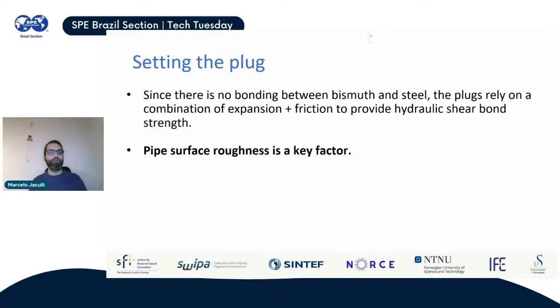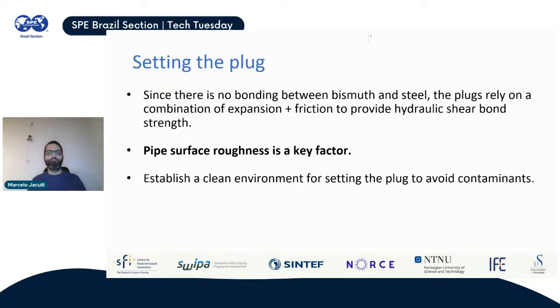So, of course, you might think, is pipe roughness something important? Yes, and it's something that we are investigating. But we do believe that depending on how you leave the casing inner wall, that roughness will be a key factor in how much pressure this plug can withstand later. And then, of course, you also need to be worried about contaminants. So if you have to clean the casing before setting the plug, you have to take these two things into consideration. You might not want your casing inner wall to be as polished as possible, because that might not allow you to set a good plug. But at the same time, you want to avoid contaminants so they don't undermine the plug strength. So yeah, there is still some discussion on what the best downhole conditions are before you set the plug.